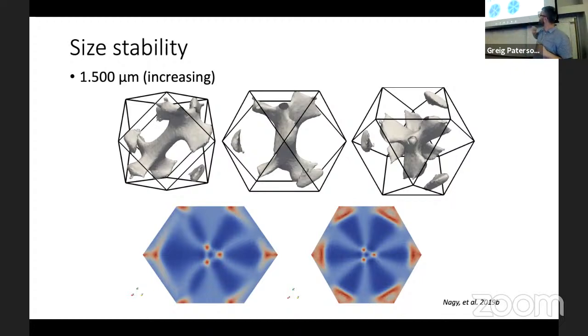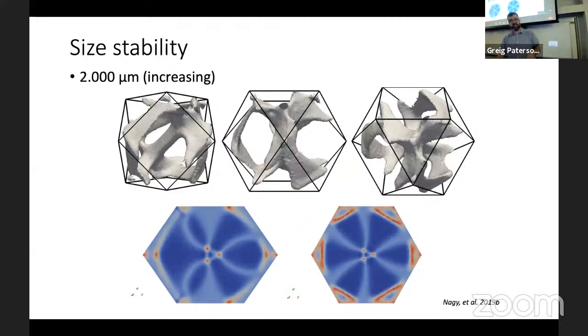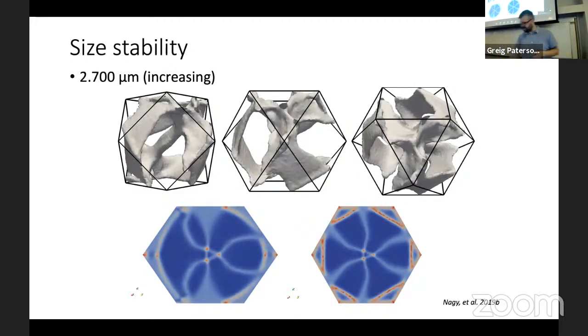That triangular structure in the middle, with the small, tiny spots, shows that the magnetization is twisting very quickly in that region, in what would be the center of the vortex core. And if we keep increasing the size further, up to the maximum size that I managed to do in this simulation, you can see that we end up with really well-defined domains with these really nice bright blue spokes that represent domain walls.